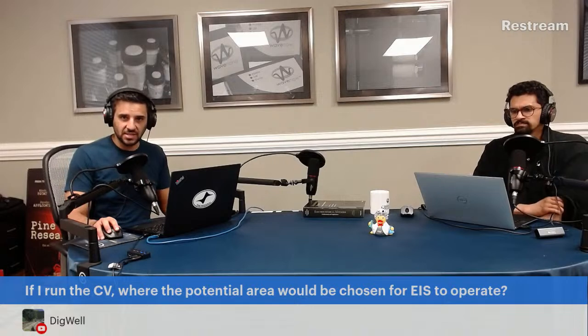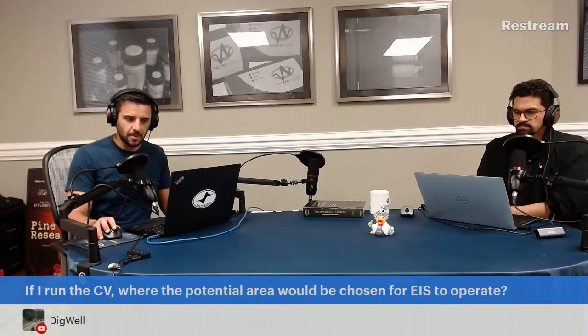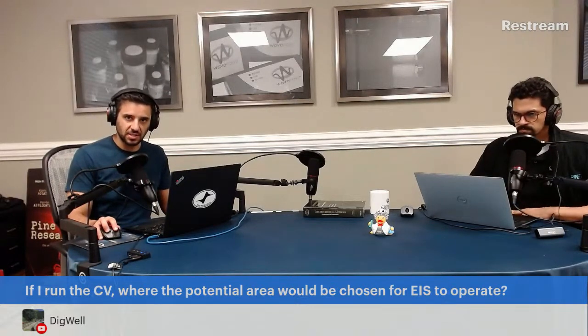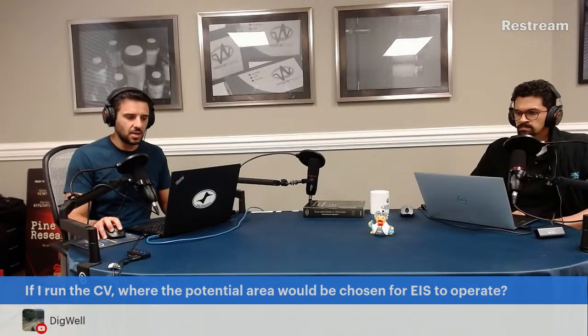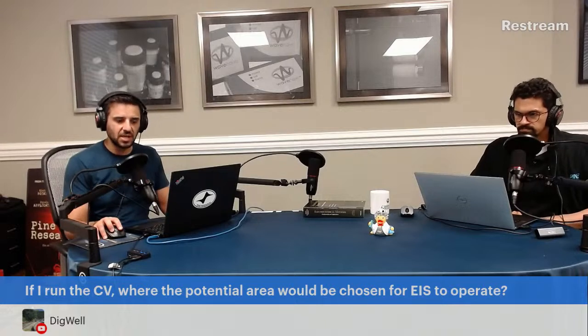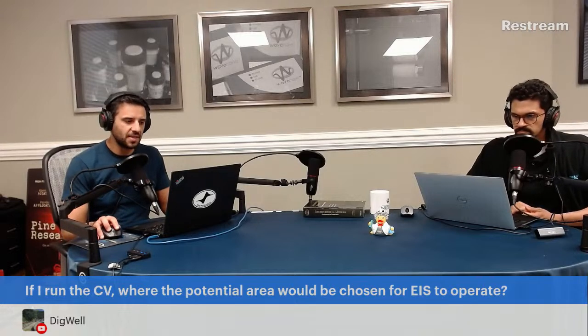And then try galvanostatic if you're not already. You didn't really specify, but galvanostatic impedance is much more successful on batteries. Typically, it's more stable, and you might have an easier time. Maybe you're doing potentiostatic and it's not going well, and that could be why. Potentiostatic impedance is not usually a good idea on batteries for a variety of reasons.